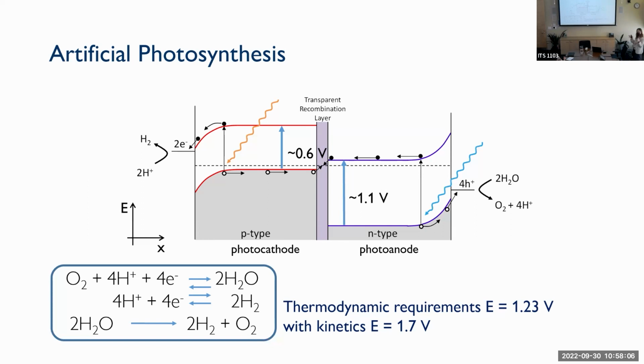We do that by utilizing semiconductor materials. So again, just think about taking a solar cell. It's a very similar concept. In this case, we have a junction. We have an N-type material and a P-type material that are put together. And the reason why you want to have a junction is because you need one side of your device to catalyze water oxidation and the other side to catalyze water reduction.